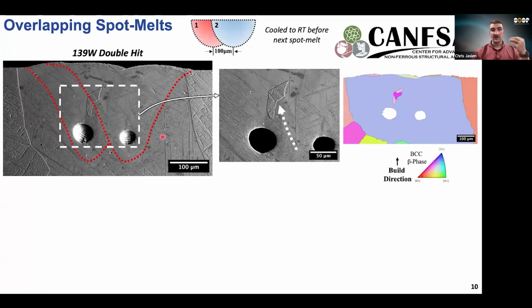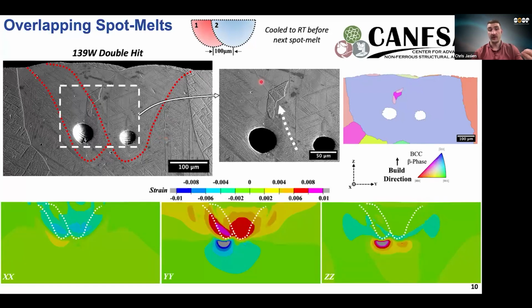And just to confirm that there's no other microstructural or atomic features that are maybe inhibiting this, we perform some other characterization techniques which allow us to see grains as well as how those grains are oriented in space. And what we see is that there is this artifact here. However, that's not really affecting this gradual process. So to us, that says, okay, maybe there's a reduction in strain going on. So when we go back to our models for this experiment, that's exactly what we see.